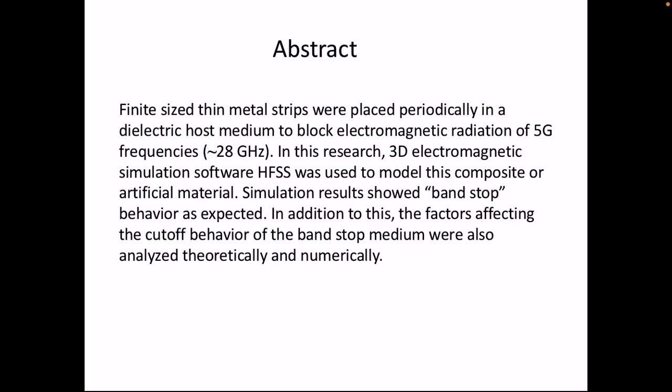Finite size thin metal strips were placed periodically in a dielectric host medium to block electromagnetic radiation of 5G frequencies. In this research, 3D electromagnetic simulation software HFSS was used to model this composite or artificial material. Simulation results showed band stop behavior as expected. In addition to this, the factors affecting the cutoff behavior of the band stop medium were also analyzed theoretically and numerically.